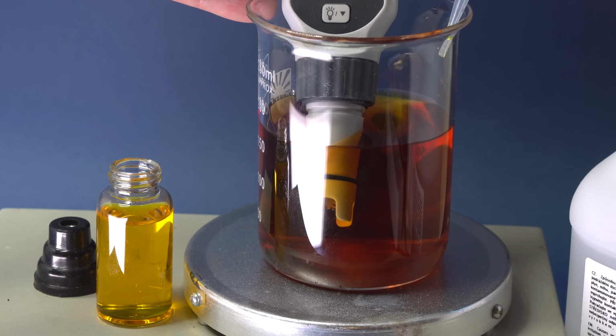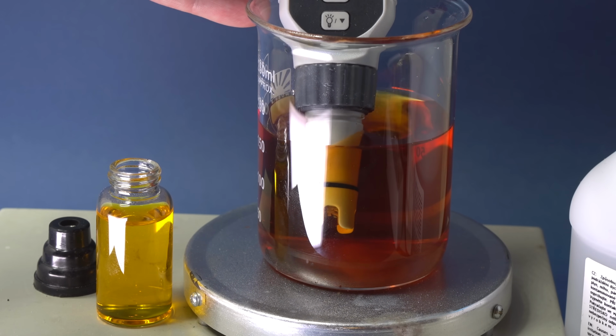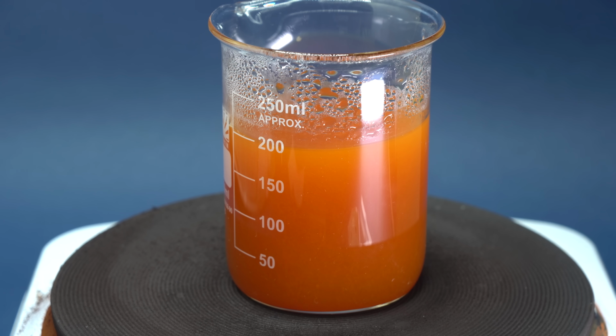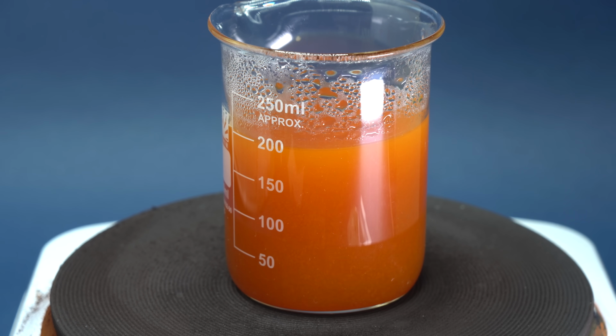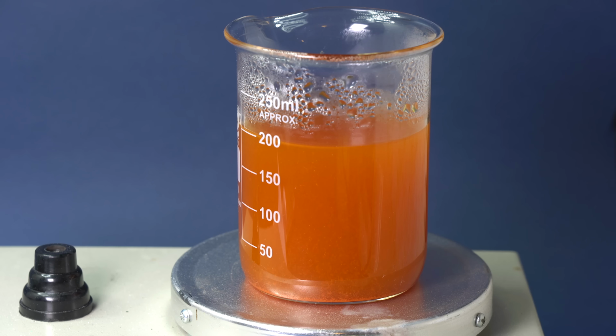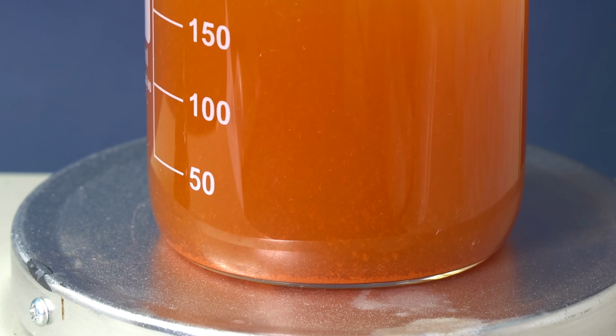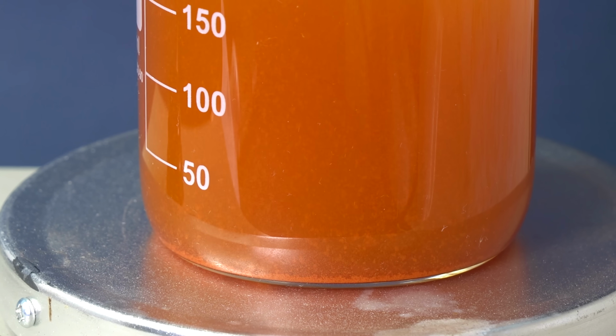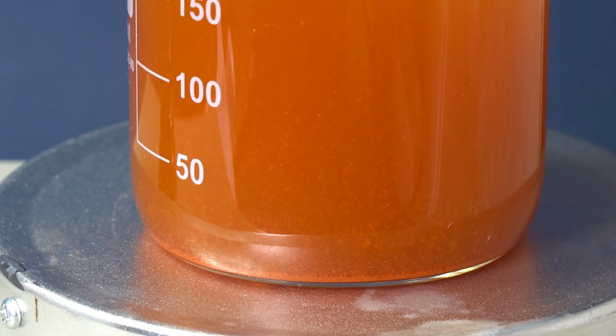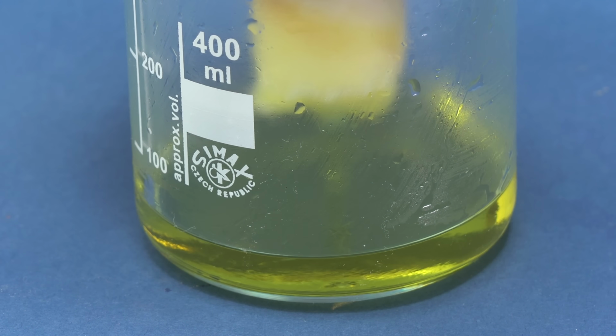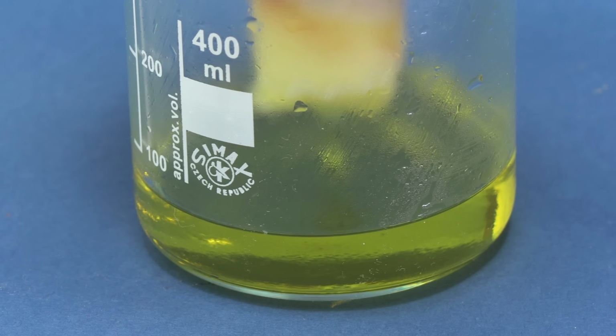The color is gradually changing, and in order to finish the reaction, I'm going to heat the solution for 30 minutes more. When I'm doing that, exchange reactions are taking place in the solution. Atoms of gold are substituting atoms of iron in the potassium ferrocyanide and are forming potassium dicyanoaurate and iron hydroxide sediment. After filtering, I got a pure electrolyte for gold plating.